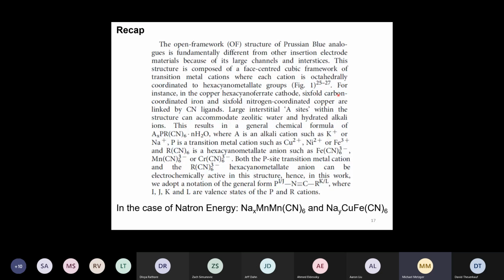So a 6-fold carbon coordinated iron, right? Those were the red balls in our model, and then a 6-fold nitrogen coordinated copper. And we have these CN ligands that build up the cubic structure. So we have these large interstitial sites, they're also called A sites, within the structure that can accommodate zeolitic water, so this interstitial water, or hydrated alkali metal ions. And then the result is a material with the general chemical formula.